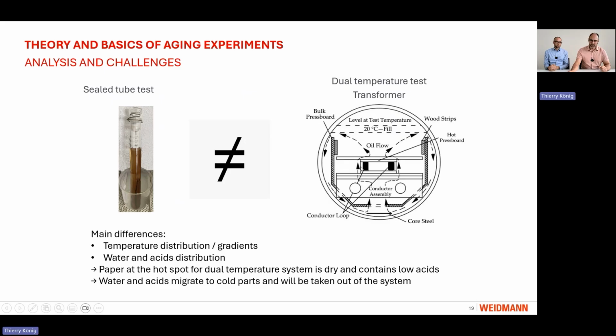What happens, for example, with the water? So we have here the hotspot. The water will migrate to the cooler pressboard here at the edge, and the hotspot is in this system always dry. At the end, if no water is there, there is also no water for the hydrolysis of the insulation, and at the end a slower aging.